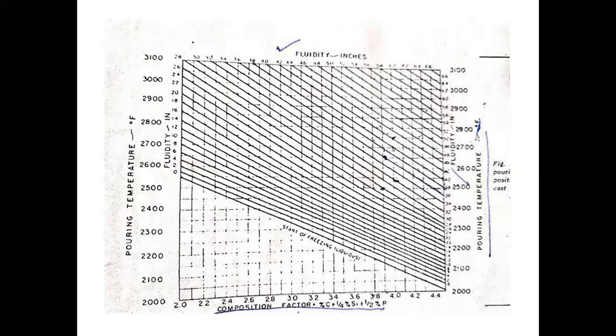Sir, one other thing, you mentioned pressurized and non-pressurized. You mentioned that for gray iron, pressurized is preferred. Yeah, for SG iron, non-pressurized, yes, because in SG iron, the carbon equivalent, though it is high, because of the magnesium, metal becomes cold very rapidly. If you compare with cast iron, in SG iron metal becomes cold very rapidly. That's why we have to pour fast, ductile iron, use a filter and pour fast. Definitely. It is proved. No doubt about it.